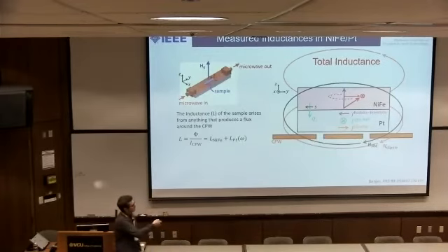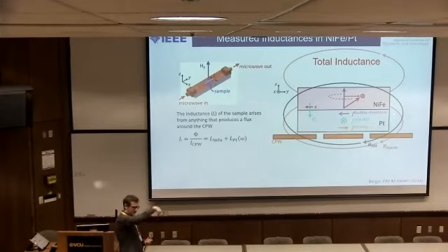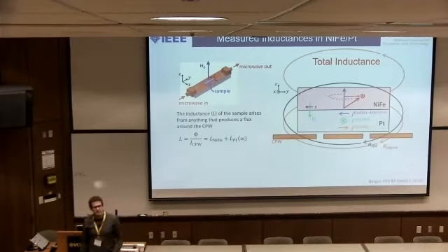In the case of the Rashba-Edelstein effect, because of the symmetry, that charge current at this snapshot in time will be in this direction. For the spin Hall effect, the charge current will be into the plane of the film as shown right there. And of course, if you have a charge current going this way, that's going to create an Ørsted field that will then couple to this waveguide as shown there.